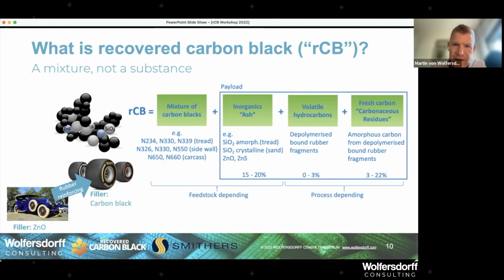Also, for the inorganic content, we could have crystalline silica, which is coming just from sand debris. The end-of-life tires, typically they're put somewhere, not in the cleanest warehouse. They might have been in the landscape. They might have attracted soil and sand. Some tires are even put underground. So there might be debris. And really, if you want to have a chemical industry product, recovered carbon black, we need to make sure that the feedstock is as clean as possible, and that goes as far as washing the tires and washing the tire granulate before they go into the pyrolysis to avoid crystalline silica. Crystalline silica in Europe is less of a problem. I don't think in Asia either, but it's very high on the radar of authorities in the US. Because we get to milling a bit later on.